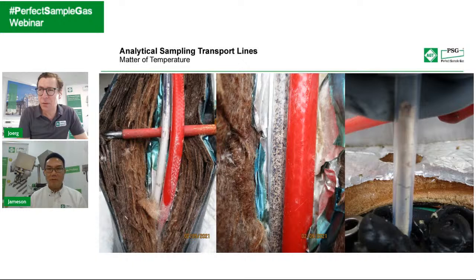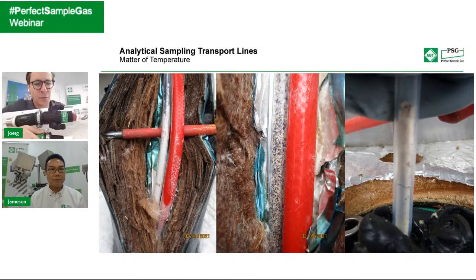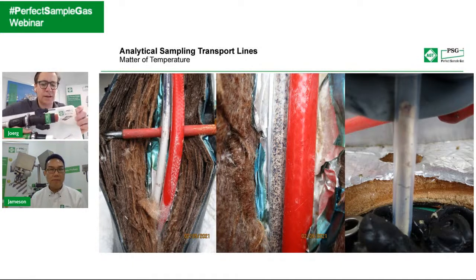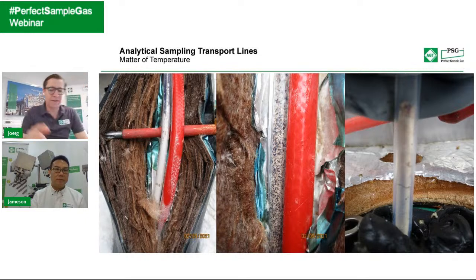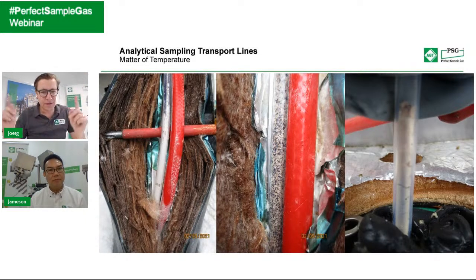So Jameson, maybe quick fix is difficult there, but whenever a customer contacts us with problems in the heated sample line, we would recommend to use an infrared camera and really try to measure the temperature of the heated sample line. Depending on what technology you use, with a fixed resistant heater, you have the situation that it's either working or not. So if this is not working, you will see immediately. But you might have a zone heater cut to length, and if a zone is not working, you will not see that in the power consumption. So in this case, you would need an infrared camera in order to check if the temperature is still there.